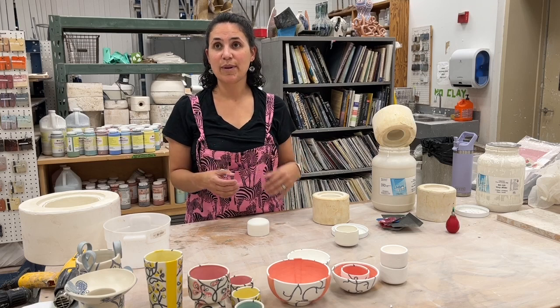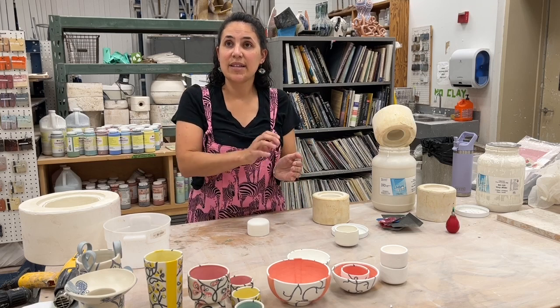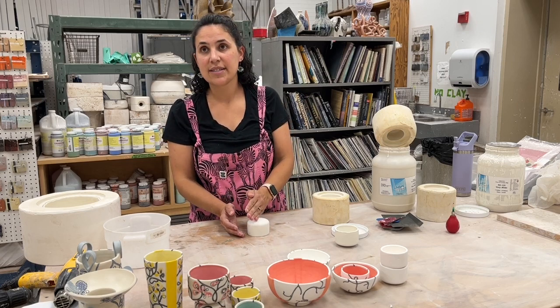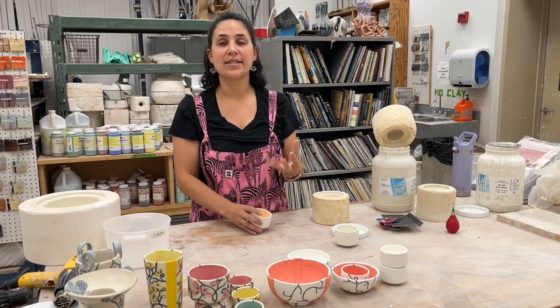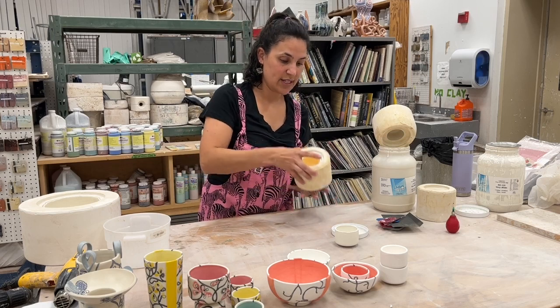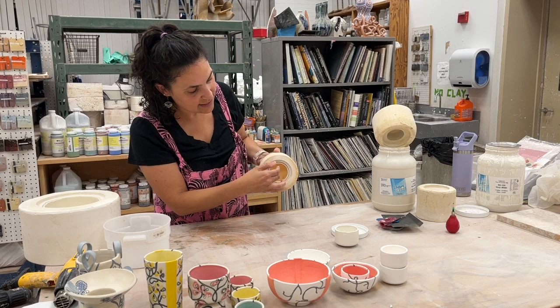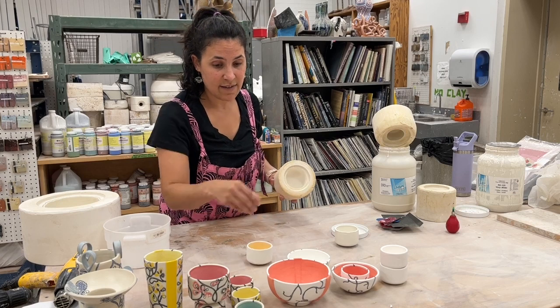The heart was a more complex form — a four or five piece mold. You have to block the different areas as you go because you've got to watch out for undercuts. If it can't lift cleanly out of the area it's going to get stuck. It does shrink a little bit when coming out of the mold — you can see there's a teeny bit of wiggle room and this hasn't even been fired yet.